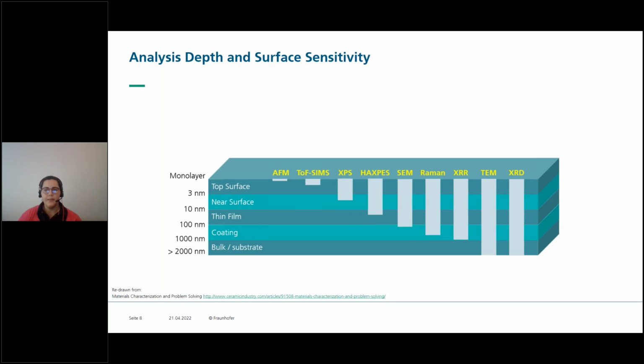Here, I just want to show examples of the limitations of the analysis depth for the types of methods that I already mentioned. For example, atomic force microscopy, TOF SIMS, XPS, HAXPES, SEM, Raman, XRR, TEM, and XRD. And here, the spot sizes of these techniques are not to scale. It's just to show you the different analysis depths. And it is evident here that XPS is a surface sensitive technique in comparison to some of these techniques. In our work at the Institute, we do deal with thin layers on average of 10 nanometers, and this is exactly the type of method that we need for our application.